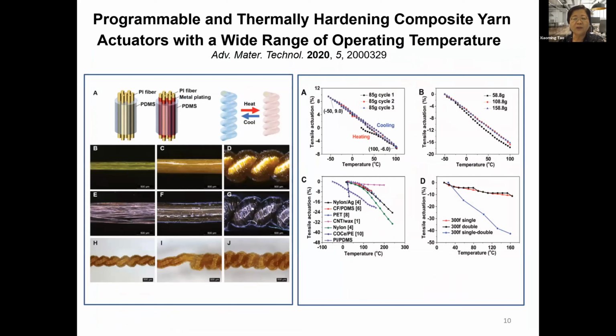Now, a fabric actuator can have a large deformation, create holes or change shape, but the reactive force is very small. And therefore, for a lot of applications, we need a large energy density and a large reactive force. The current technology, one of them, uses curved monofilament fibers like this. Normally it's made of nylon fiber or low density PE fiber. And they are nice, they have a large deformation, at the same time high energy density, and also reactive force. However, they cannot work at a low temperature. They start from room temperature up to maybe 100 degrees maximum. Then they stop working.